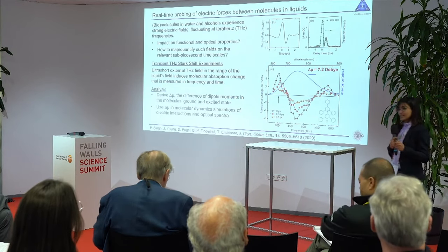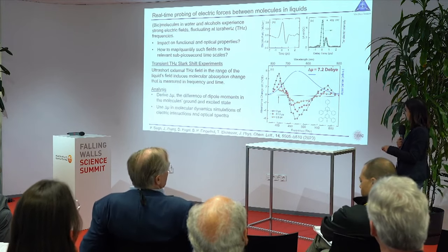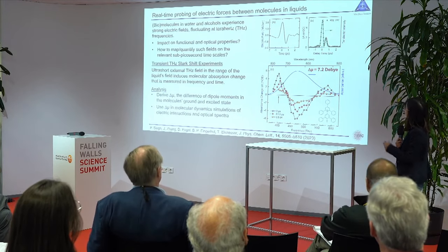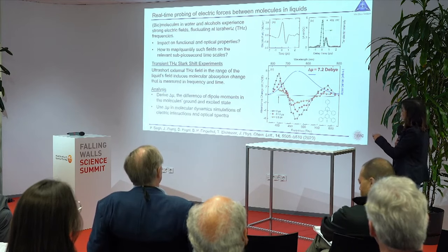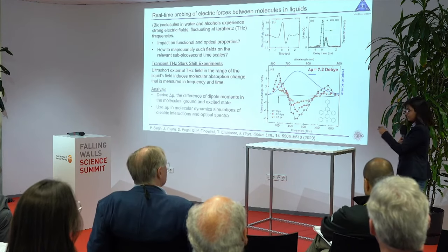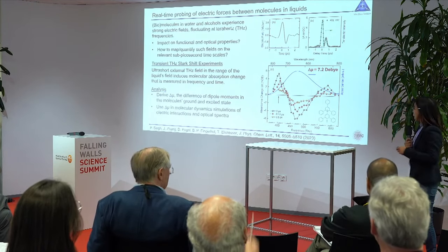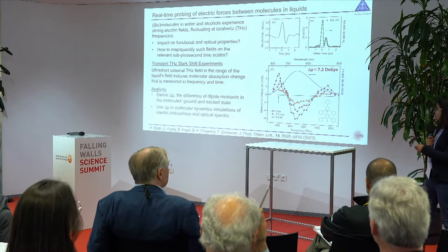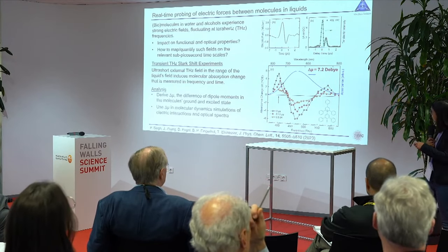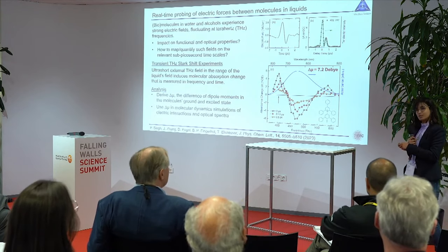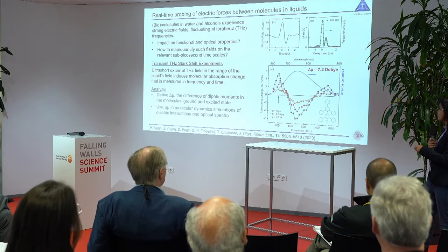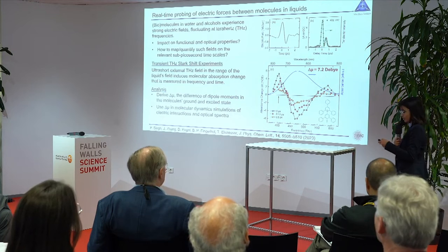Now, if we take the time evolution at a particular probe frequency, which is given by the arrow here, we see that the absorbance changes follow the terahertz intensity in time. By taking the numerical analysis of this spectrum, we calculate a dipole difference value of 7.2 debye between the excited and the ground state for this particular chromophore.